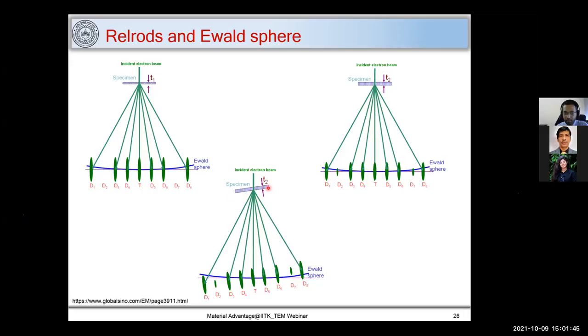Now let's say I tilt my sample, and that's what we do in TEM, we tilt the sample. When there is an Ewald sphere which is cutting, you can see here that this Ewald sphere is cutting through some of the rel rods. Now, this rel rod has not been cut, so this point will not diffract at all. This point will diffract to a maximum intensity. This point will diffract to a lower intensity than this. And here you can see that the deviation parameter is positive because this point is inside the Ewald sphere. So that's why this deviation parameter is positive, while here the deviation parameter, that is S, is negative.